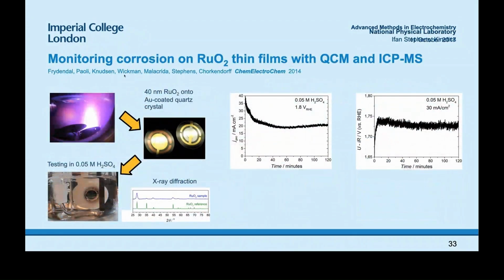We did an experiment where we made a ruthenium oxide catalyst. We deposited it onto one of these quartz crystal microbalances and measured the current as a function of time. What we could see is that after about 2 hours, we get very, very stable electrochemical performance. Similarly, when we hold a constant current and measure potential, we see a very stable potential with time.